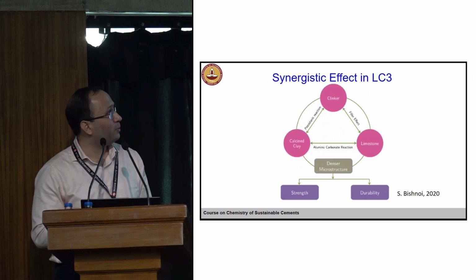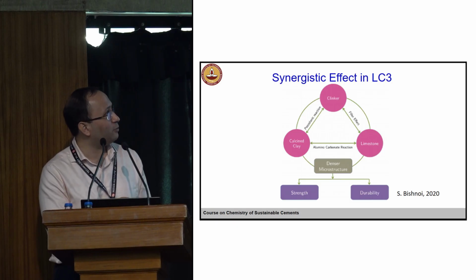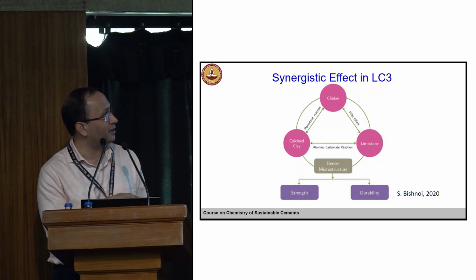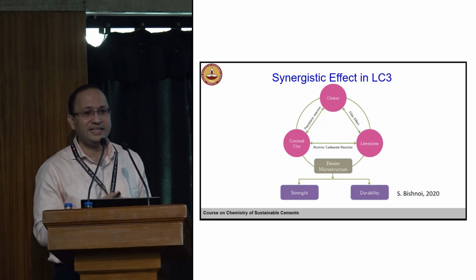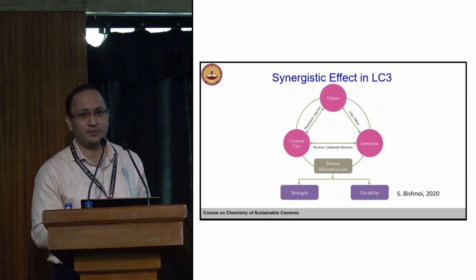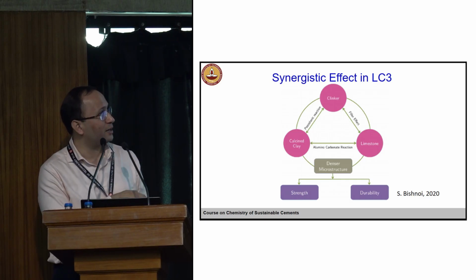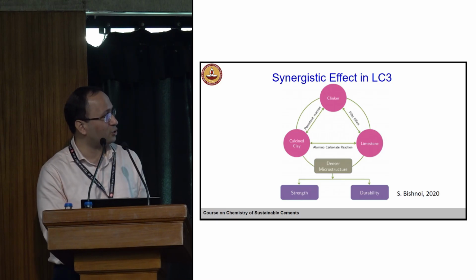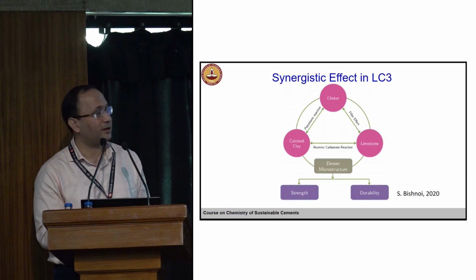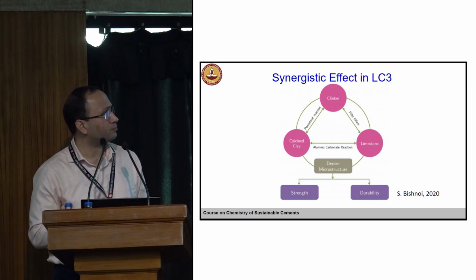This is a slide borrowed from Professor Shashank. It shows kind of a synergistic effect in LC3, right? When you have calcined clay and limestone, you have these aluminocarbonate reactions. You have also pozzolanic reaction. You have filler effects. All physical and chemical effects are present in the system, right? Not just filler effect, but also these chemical effects. And overall, it leads to a denser microstructure, leads to better, higher strength and durability.